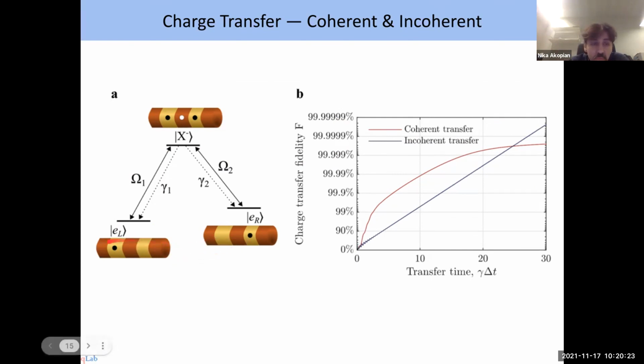The incoherent way is very simple. So we have this electron here, and what we do, we simply excite this electron hole pair. So what can happen? We excite this one, okay, this can recombine back and nothing happens, so the electron is left here. But when you excite this one, also this pair can recombine. And when this pair recombines radiatively, a photon is going out, and then you are left with an electron on the right side. So simply by exciting this transition, and again, by waiting, you can destroy the electron on the left side and create an electron on the right side. That's why we call it incoherent. We create one and destroy another one.